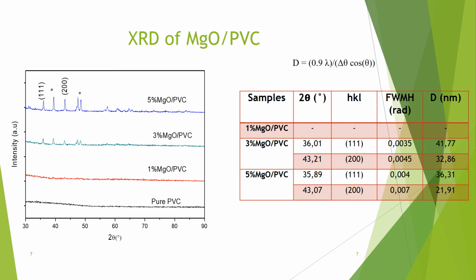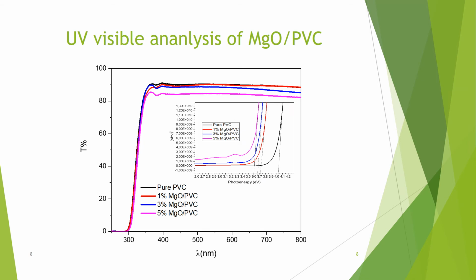From the table of structural parameters of magnesium oxide PVC, we can see that the grain size ranges approximately from 21 to 42 nanometers. The optical energy band gap of all films was determined using the Tauc plot method. We found that the gap of PVC is 4.02 electron volts, then it is reduced to 3.6 electron volts for 5% magnesium oxide PVC.